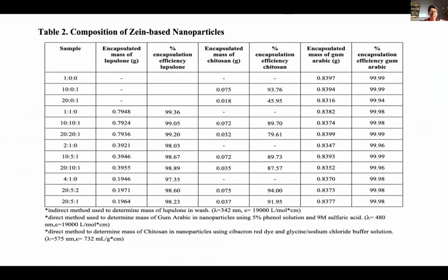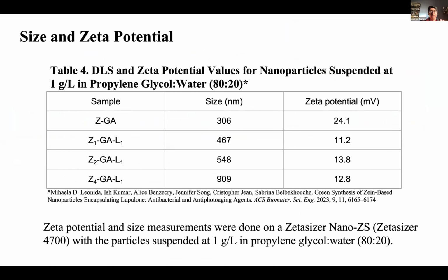Table 2, you can see the composition of our nanoparticles after we had already tested everything. You can see encapsulation efficiency is high for lupulone, it's high for chitosan, and it's high for gum arabic. Here I included some nanoparticles that were tested for their size and zeta potential from a previous study. This is just to give you a reference of the size of the nanoparticles.